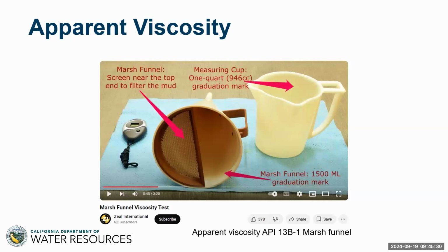Apparent viscosity. Again, those of you who have worked in the oil field probably use this a lot. Basically, it's a funnel that you can see lying on its side there with a handle. It's got an aperture at the bottom. You take some of the grout, you pour it through the little mesh there. You put your finger first, of course, over the orifice at the end, then you take it away, you start timing, and you're timing the amount of seconds that it takes for 1 quart of grout to pass through.